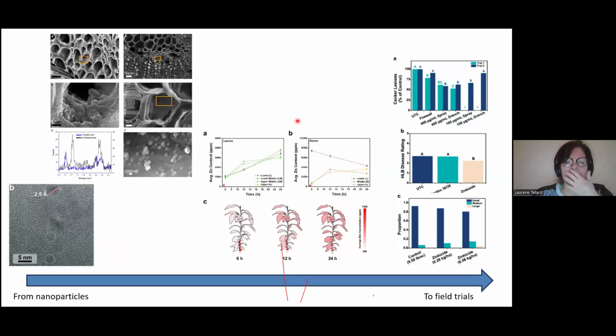Another thing we did at the microscale, or the small plant level, more on the plant side, is that we exposed seedlings to the treatments, and then we sectioned different segments of the seedlings, and we used all our imaging techniques to try to track whether we could find signs of the nanoparticle in the vasculature to understand whether the treatment is indeed systemic or not. So we were able to confirm that.